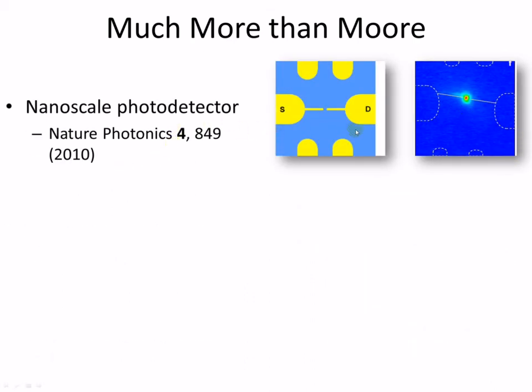So the nanoscale photodetector work was recently published. The idea is you create a wire and you cut it, and that junction becomes sensitive to light. You can close the switch not using a third-terminal gate, but rather using a focused light beam. It turns out to be a very sensitive detector that's tunable with the very large electric fields applied between source and drain. And it's interesting for molecular-scale spectroscopy.